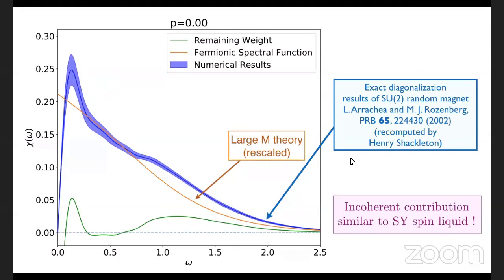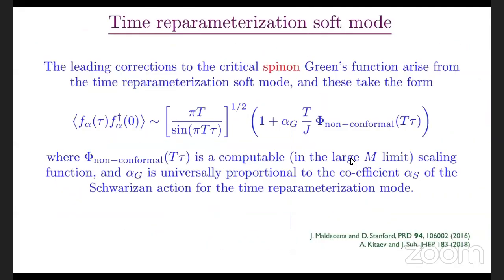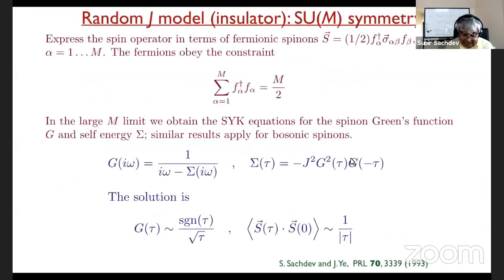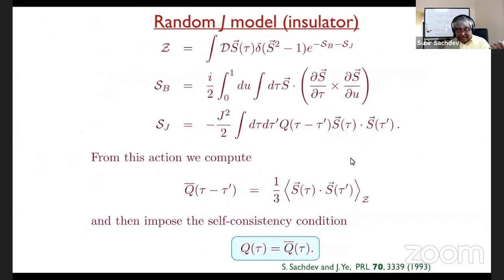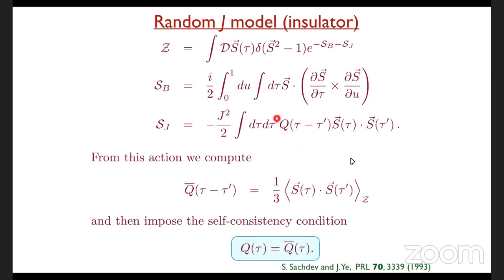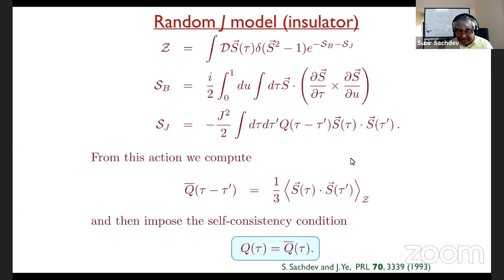So the key to the time reparameterization symmetry is not only that you have a critical point, but also this self-consistency condition. That's crucial. There is no other power law source other than the self-consistency itself. So this self-consistency condition is the key to the time reparameterization symmetry. Because then you see that the action that you write down doesn't have any external power laws. If you integrate out the environment in a Kondo problem, you get a 1/tau to the alpha long-range interaction in your impurity model. Once you do that, you've lost your time reparameterization symmetry. So in this case, Q is itself kind of like a dynamical variable, and that's why there is no explicit time dependence in anything, even when you reduce it to a zero-dimensional problem. And that's the key to the time reparameterization symmetry.